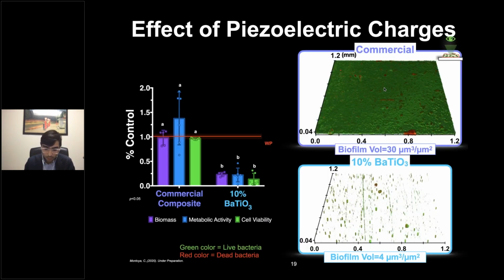We did the same exercise. We went to the fluorescent microscope to see if there's any biofilm. Commercial again is showing a very nice layer of roughly 40 microns of biofilm. But when we check for the same features on the BTO, there is none of that. You begin to see a tiny bit of live bacteria here and there, but there's pretty much nothing on that surface, which was very exciting.